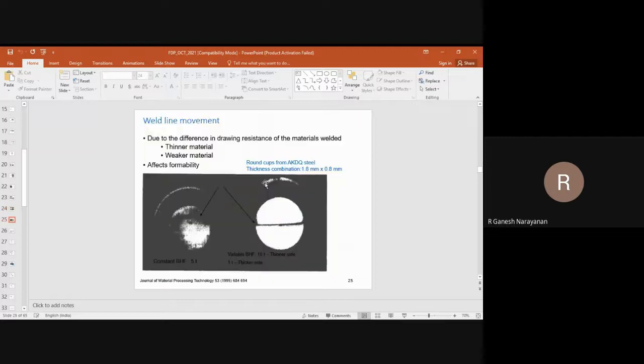welding process. Now, there are some problems in welded blanks. One important problem, of course, forming limit is reduced, ductility is reduced, you have to enhance it, all those things are fine. Typically, the weld line moves. When you do, let us say, deep drawing, the weld line is not going to be at one location, the weld line is going to be at a different location after the component is made. For example, you can see here, this round cup is formed, okay, wherein you can see that the weld has to be at the center, right? But you will see in the first photograph, the weld is at a critical location. In the right side photo, the weld is at the center. That is because they have done something on the process.